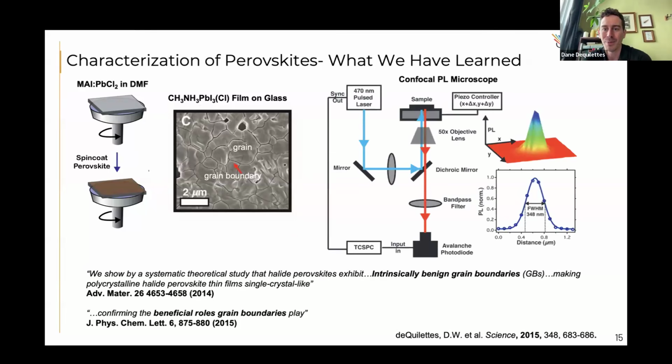I had built a confocal fluorescence microscope in order to create these really detailed images of what the photoluminescence looks like around these grains. These are much higher resolution than the images that we were looking at from, let's say, BT imaging and Thorsten Trupke's work, because we're focusing the laser to a diffraction limited spot size and then scanning it to create a PL image.